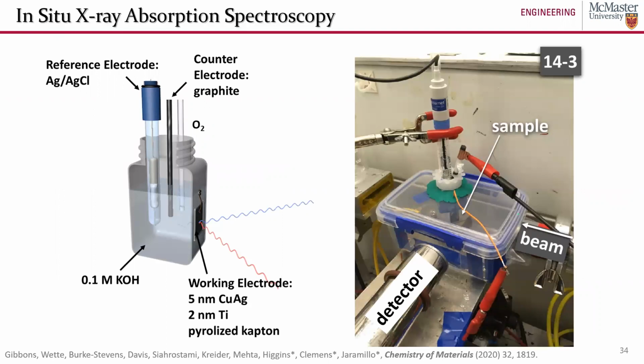So we packed these materials up, and we designed an electrochemical cell that would allow us to get X-rays into the copper silver thin films and get fluorescence out from the copper silver thin films using a technique called X-ray absorption spectroscopy. This is a synchrotron-based technique that we were doing at SSRL down at the SLAC National Laboratory in California. And we designed a reactor where we needed to have a reference electrode in it. And so we designed a reactor that could accommodate a conventional silver chloride reference electrode.